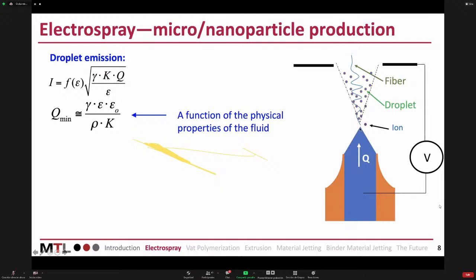So you have your spray, you can generate droplets, fibers, or ions, pretty much depending on where you're operating and what the working liquid is. The simplest operation mode would be droplet emission. And in that case, there is a clear correspondence between the current that you emit and the flow rate. And this minimum flow rate is based on the actual liquid that you're pumping. But if you're going to do ions, which is something that you'll be interested in, for example, if you're doing space propulsion, then you deal with liquids that are a lot more electrically conductive, and you deal with flow rates that are a lot smaller than what you do with droplet emission.